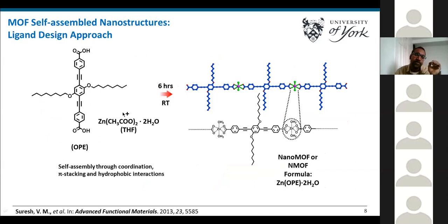We take these two components, zinc acetate and OPE linker, and mix them in THF for 6 hours at room temperature. We see the formation of stable colloids where the zinc binds to the linker in a 1:1 fashion through zinc carboxylate. This is proved from elemental analysis and IR analysis of the bonding.